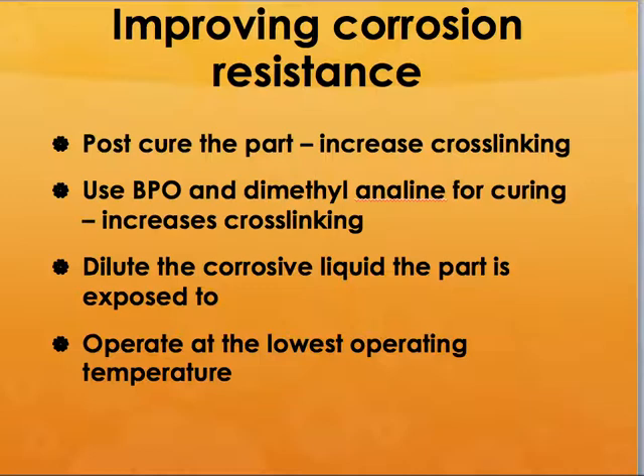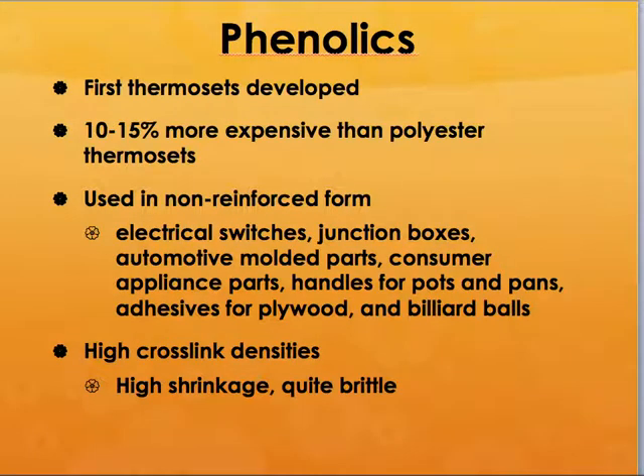So in order to increase the cross-linking, you have to post-cure the part. And or if you use benzoyl peroxide and dimethyl aniline, then that also can increase the cross-linking. And or you can dilute the corrosive liquid the part is exposed to, but that is not always possible. Or you might also want to operate it at the lowest operating temperature. But the last two bullet points are probably not possible. So what you do is the first two bullet points: you post-cure and you use benzoyl peroxide and dimethyl aniline to do the curing, which increases the cross-linking ratios.